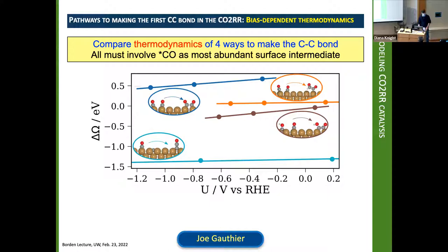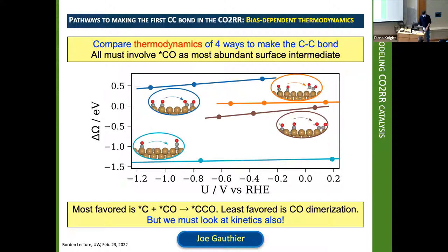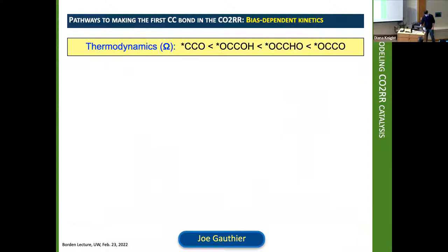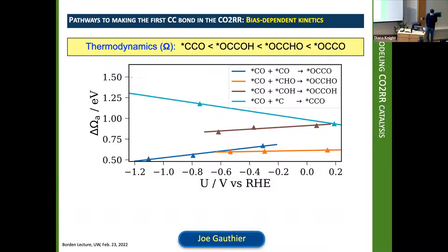So let's now take a look at the kinetics, bearing in mind that from a thermodynamic point of view, most favored is surface-bound carbon recombining with CO, least favored is CO dimerization. So there's the thermodynamic sequence that I just showed you. Now, what about the bias-dependent kinetics? As a function of voltage, here's the change in free energy of activation for the forward pathways.